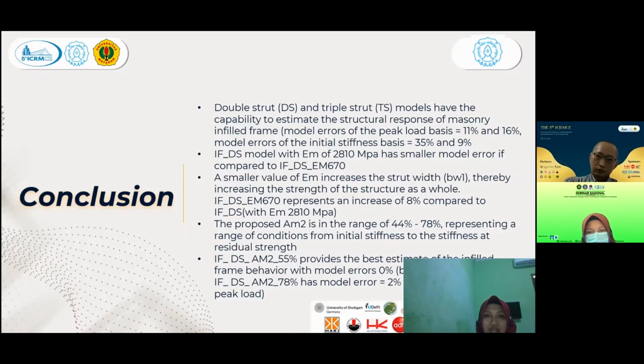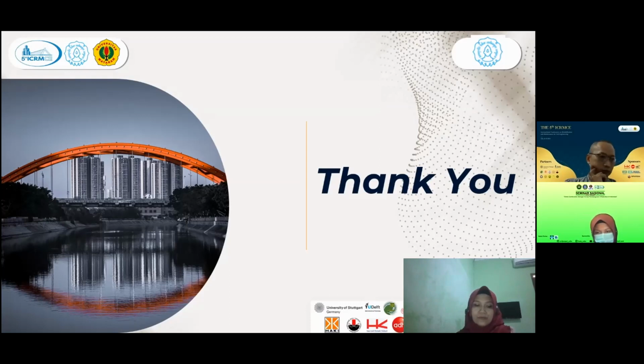A smaller value of EM increases the strut width, thereby increasing the strength of the structure as a whole. The proposed AM2 is in the range of 44 until 78%, representing a range of conditions from initial stiffness to the stiffness at residual strength. And the last, IF_DS_AM2 at 55% provides the best estimate of the infill frame behavior with model error 0% based on peak load, and IF_DS_AM2 78% has model error 2% based on stiffness at peak load. And thank you.